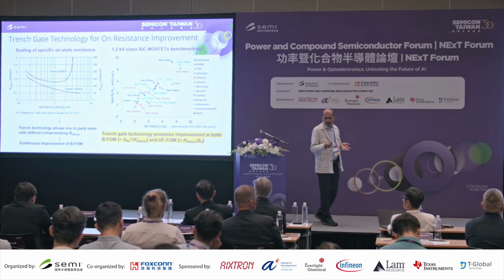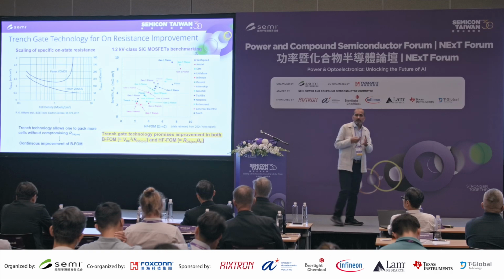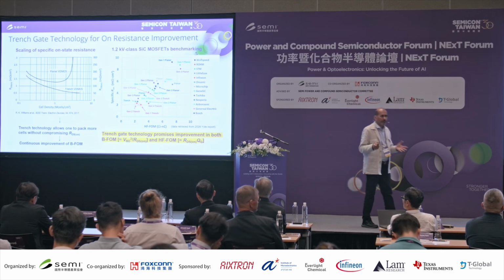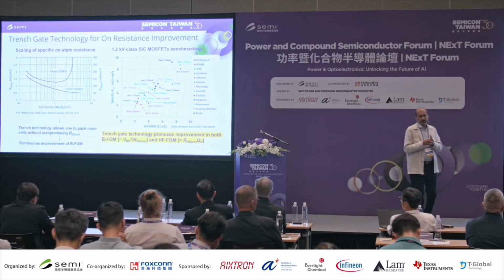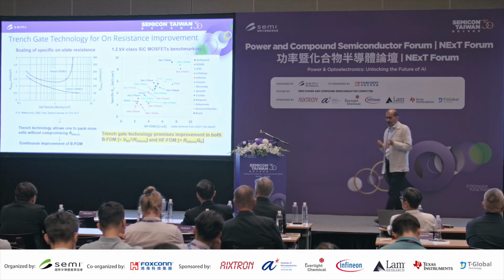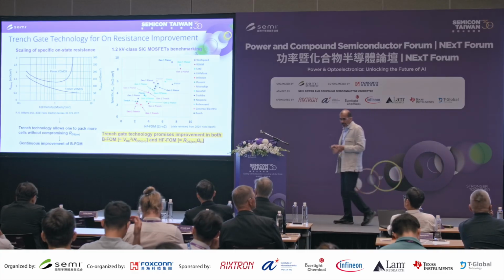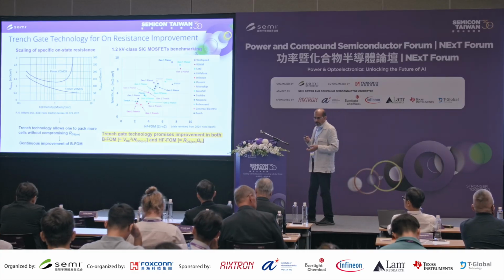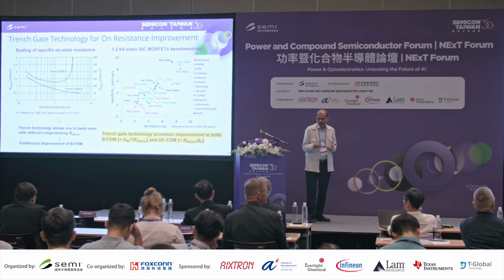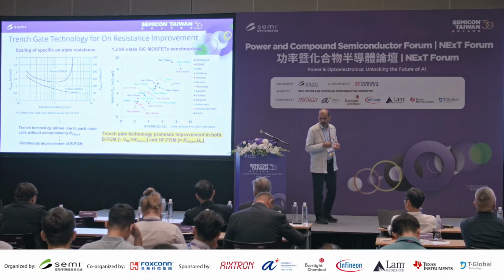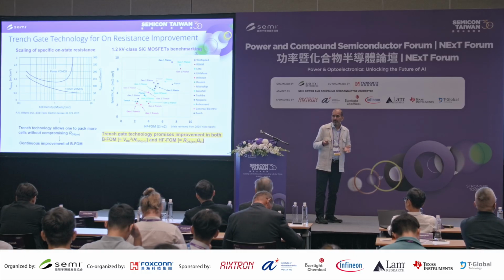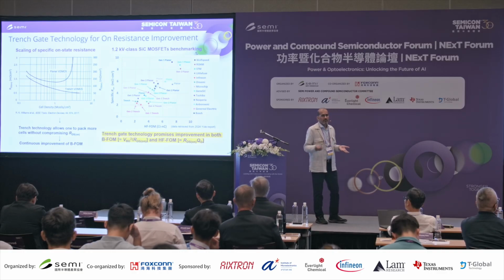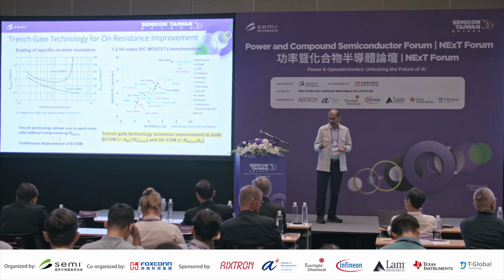While in the case of trench gate, you can keep on scaling. As long as you have good lithography and good contact, you can scale the size of the device and keep reducing the on-resistance. And on the right side, you can see that it is not only the on-resistance, which is Baliga's figure of merit, but also the high frequency performance of the trench devices is better because its charge behavior is better, its QGD is smaller.